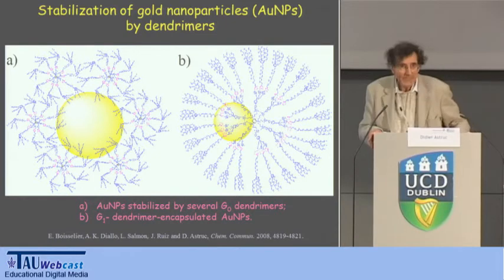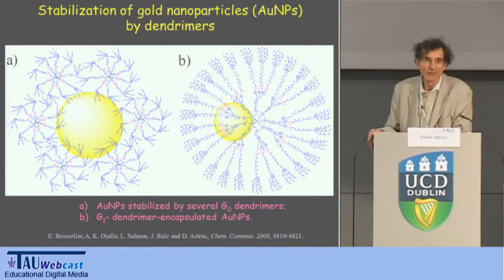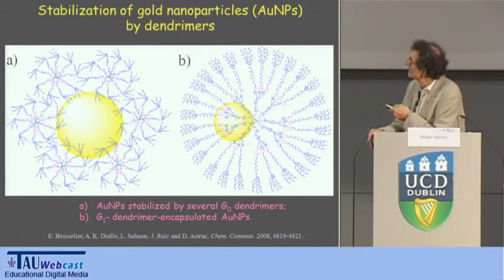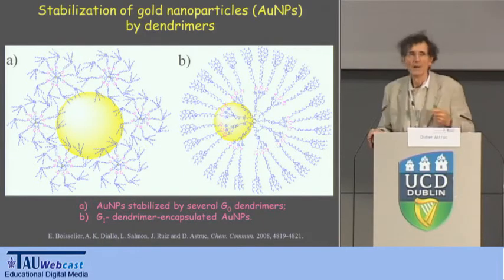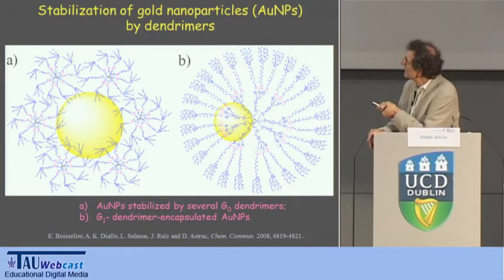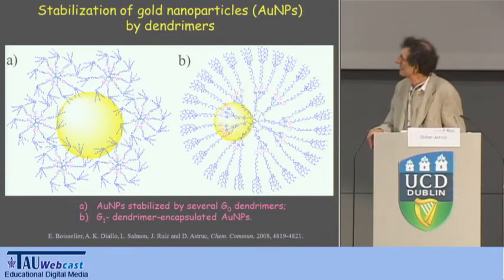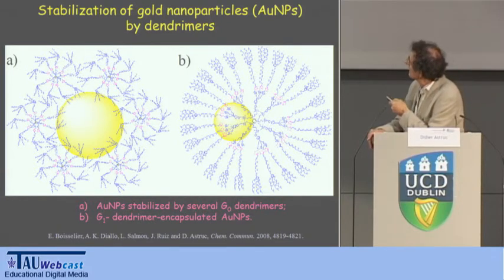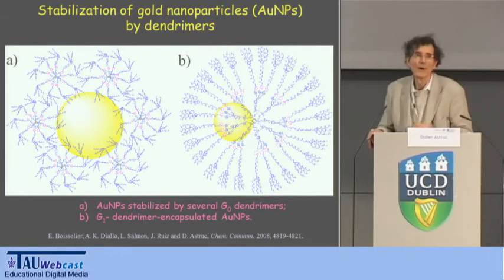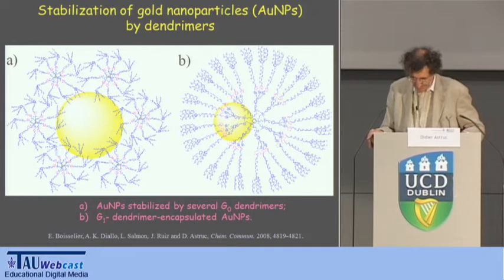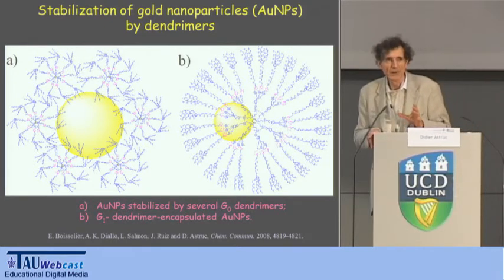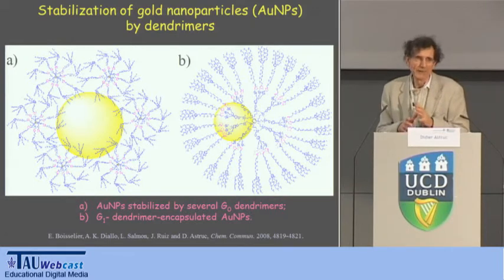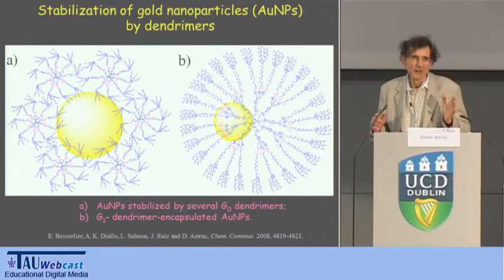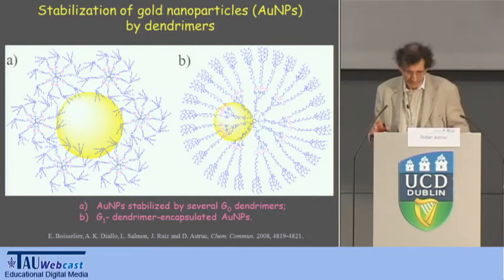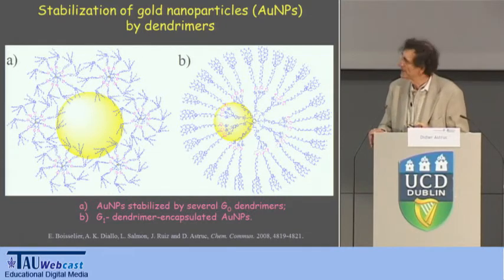So the way to make nanoparticle protected by dendrimer can be twofold, actually. With small dendrimers, you can have stabilization of a large nanoparticle, because you cannot make the nanoparticle inside the dendrimer. So you are going to have several dendrimers surrounding a large nanoparticle. And if you have a large dendrimer, then it is possible to encapsulate a small nanoparticle. So depending on the generation and size of the dendrimer, you can make a very small nanoparticle of the order of 1 nanometer to a large nanoparticle of the order of 50 nanometers. So all the scale between the two is accessible using the dendrimer technology.